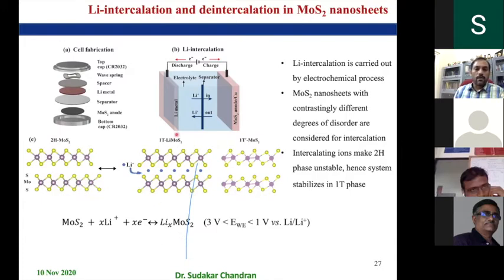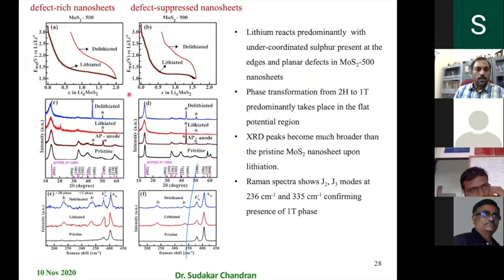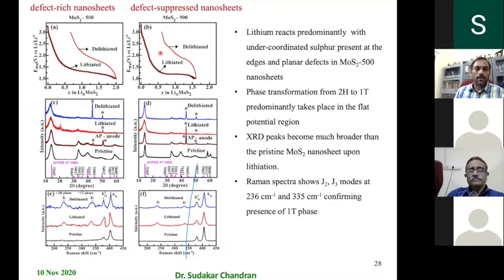So we control the voltage such that we don't go below 1 volt, in which case only a maximum of 1 lithium is possible. But even in that range, in the bulk samples, what we found is, if you have defect-rich nanosheets, this particular electrode takes up 2 lithium. In 900, we found it takes up close to 1.6 lithium. So excess lithium is taken into the system because of large edge defects, the folding, and other defects present in the system.